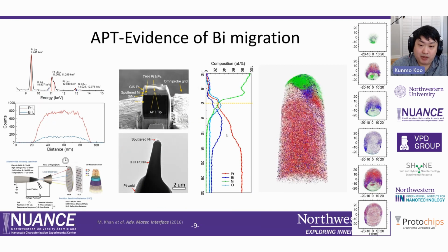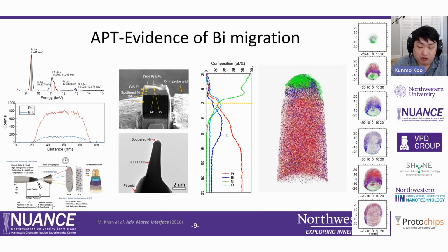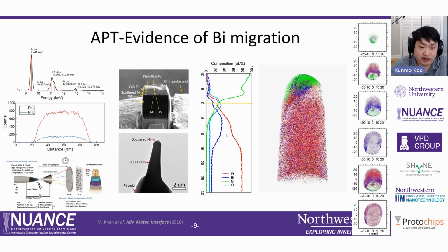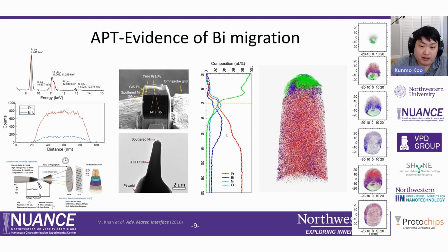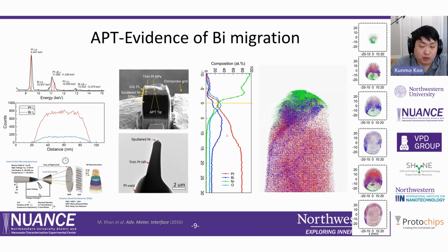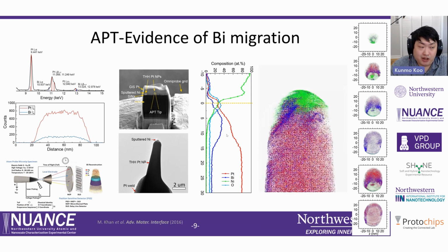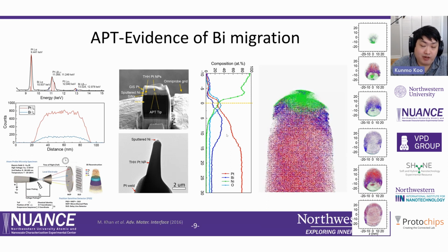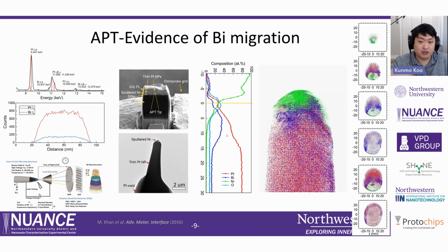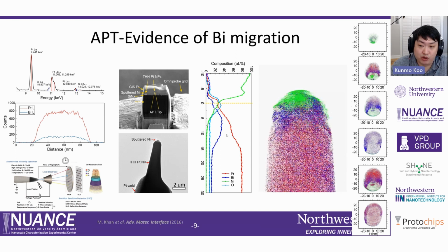To show experimental evidence of the bismuth migration, we did an elemental quantification inside the nanoparticle. Unfortunately, the most common TEM-based elemental analysis, EDS, does not work for our purpose. It is simply not plausible since they are both very heavy elements, and their characteristic X-ray spectra are so close that they easily converge together.